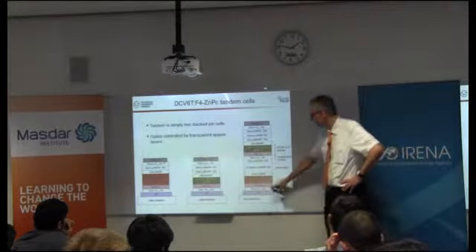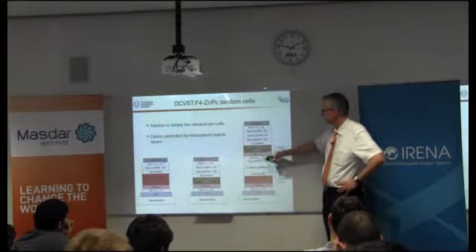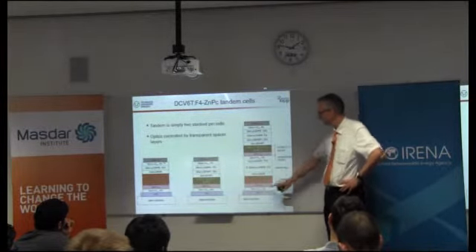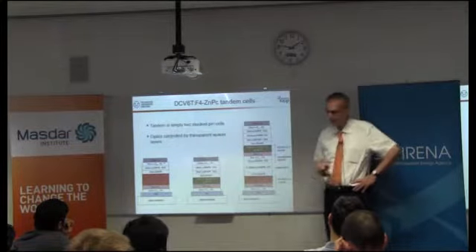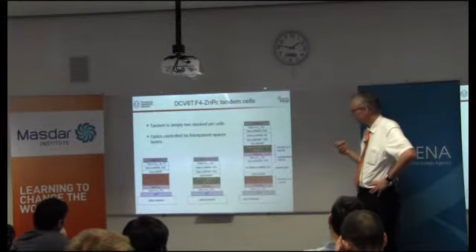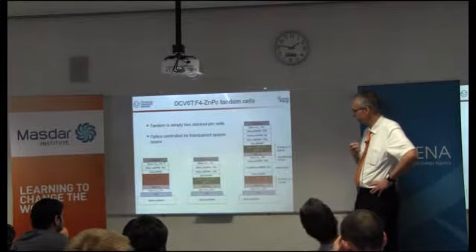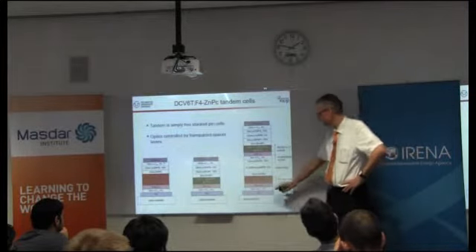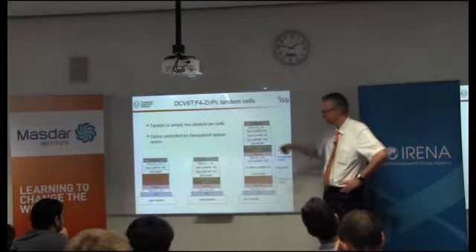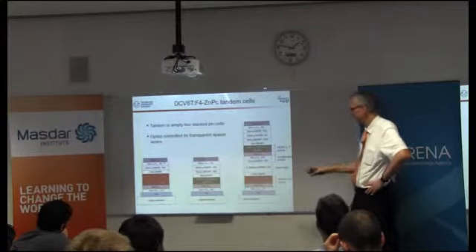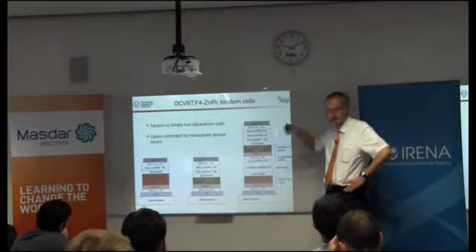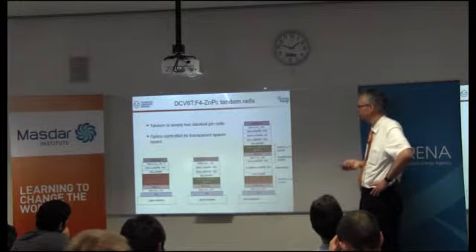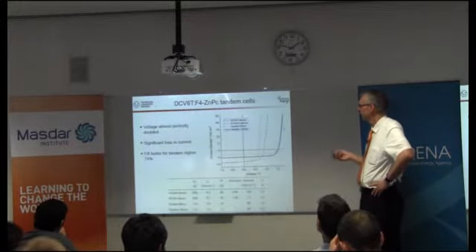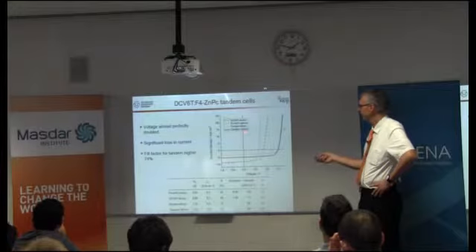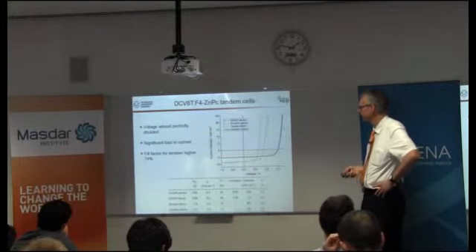Now, as you can see, we have a device which is still very thin. Many layers are only a few nanometers, but we have a 10 or 12 layer device, and the question is how to produce that. We do that by evaporation in vacuum, and in vacuum it's actually pretty easy to make such a stack. And Heliatek is doing exactly such stacks now in pilot production on a tool I'll show you in a second. And the point is, when you make the tandem, you basically double or sum up the voltages very nicely.